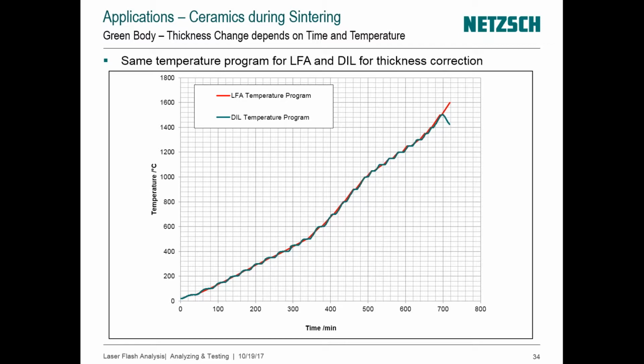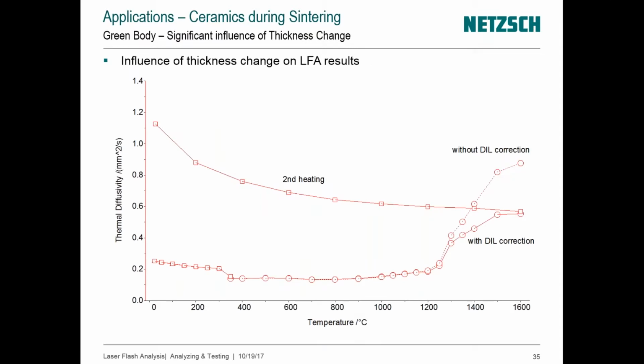When you're trying to match the information obtained with the dilatometer, it's very important to also be sure that you're following the same temperature profile. Again, this test documents the influence of knowing the true thickness of the specimen in the ceramic material. You see heating up with a dilatometer, and then correcting. First of all, not accounting for the change in thickness, what you see in the dotted curve, and then what you would see accounting for the change in thickness based on the data obtained from the dilatometer.